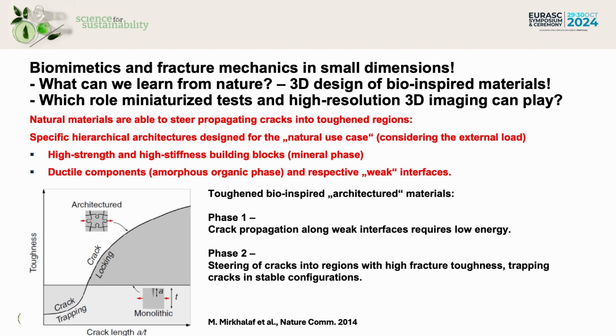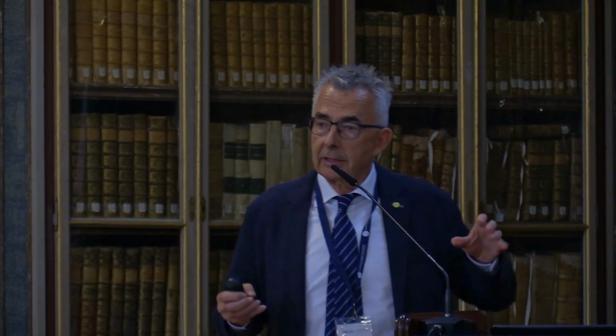We have the first phase where the crack is propagating along interfaces, and then in the second phase, the crack is steered into a region with high fracture toughness, and there the crack is trapped or stopped. So that means nature knows that we have to live with defects. Nothing is 100%. However, there are mechanisms that allow us to stop such microcracks. So this needs a composite between a high strength and high stiffness building block, that's the calcite, and a ductile component with a high fracture toughness, here an amorphous organic phase.